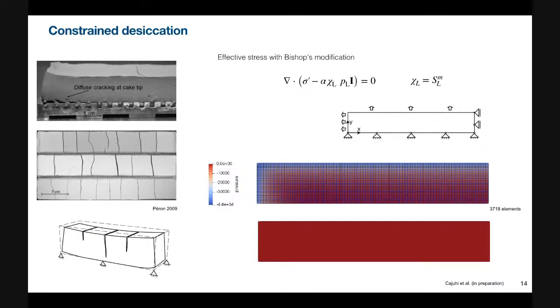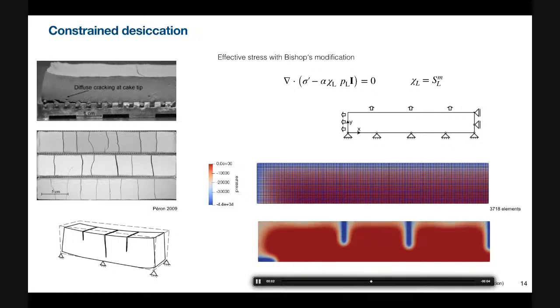Okay, another example of fracture initiation is the desiccation-driven crack. We have a saturated clay sample placed on a plate with constraints, and then we let the water evaporate. So this is an experiment, and this is the top view. We consider unsaturated flow with capillary effects. As the water evaporates, that induces negative pressure, and then the sample starts to shrink. First, we get cracking on this left corner, and then we get these vertical cracks. So this is what we simulated. First we get the left corner cracks, and then we get these vertical cracks.